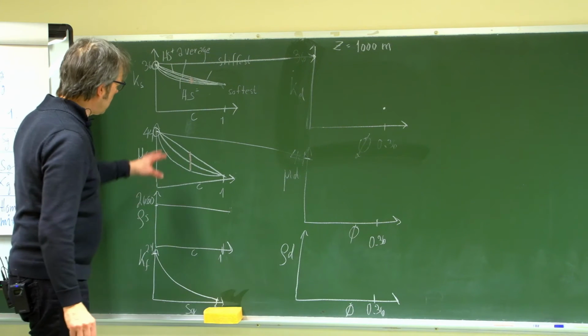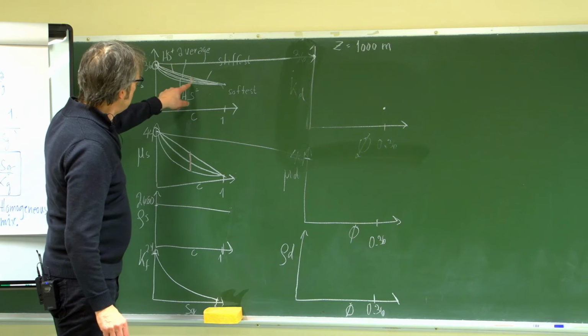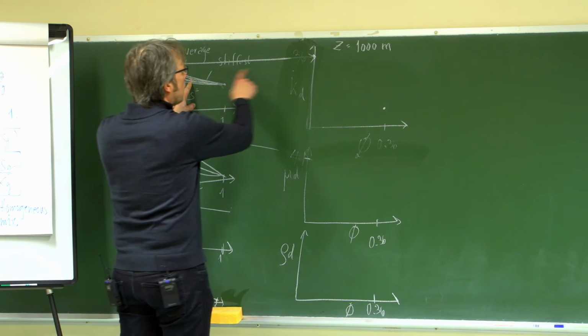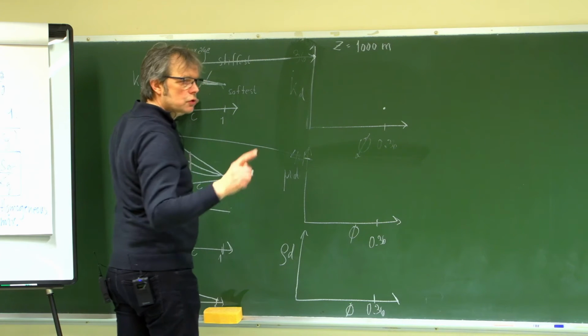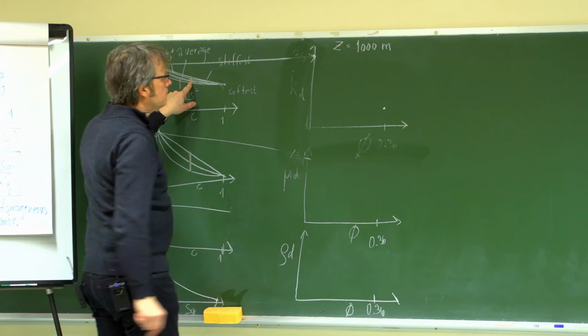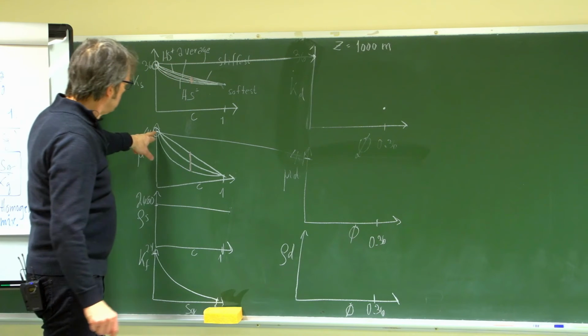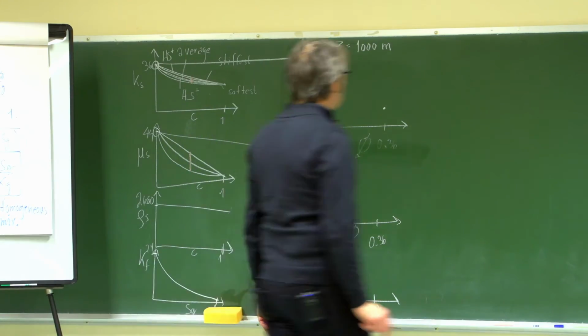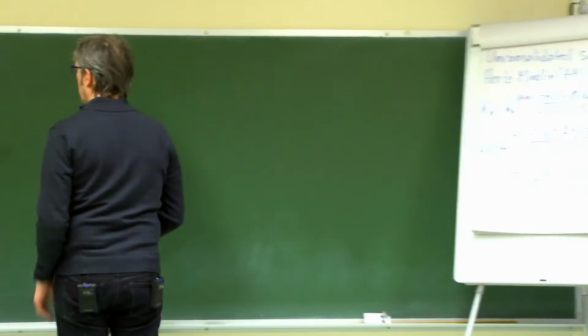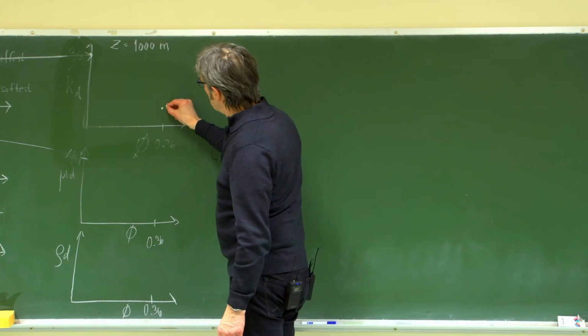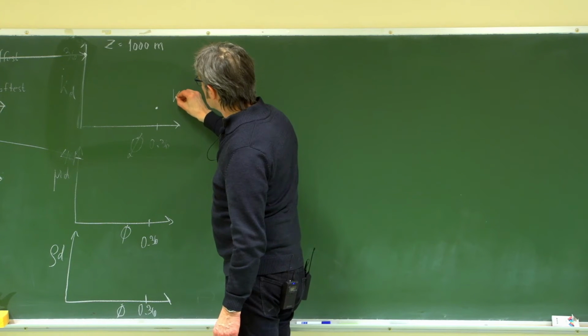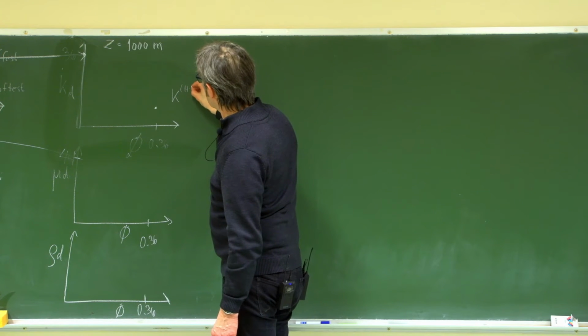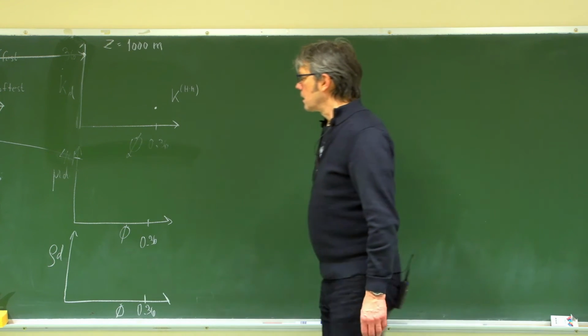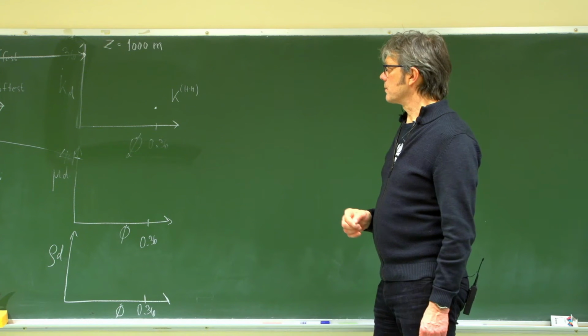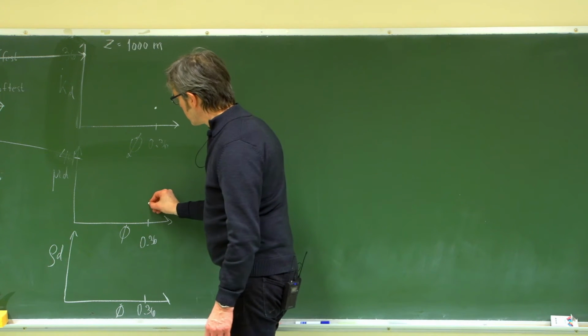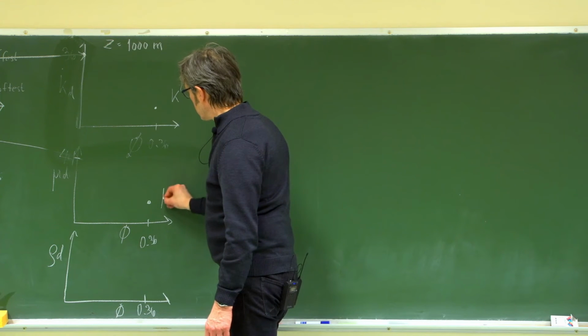So if I had selected another situation here, let's say a 50-50 soft mix, that would be my starting point. That's my solid mineral point. But in this case, we are looking at pure sand. Okay, I use this Ks and µs and end up with this point here, which I call the bulk modulus using the Hertz-Mindlin theory. We call that the Hertz-Mindlin point. It would be approximately the same here for the shear modulus.